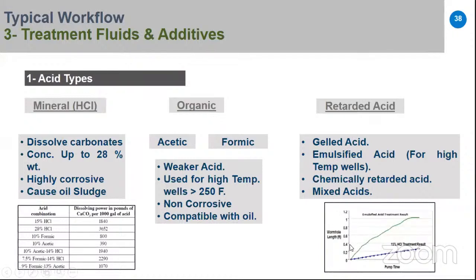So this diagram shows the difference between using HCl as a plain acid and the emulsified acid. As we see, the wormhole length increased with emulsified acid because it reduces the diffusion rate and makes the acid live longer for deeper penetration. And this is the different dissolving power for different acid systems used in carbonate acidizing. As we see, the most powerful dissolving power is for 28% HCl, and the least is for 10% acetic. It dissolves only 390 pounds of calcium carbonate per 1,000 gallons of acid.